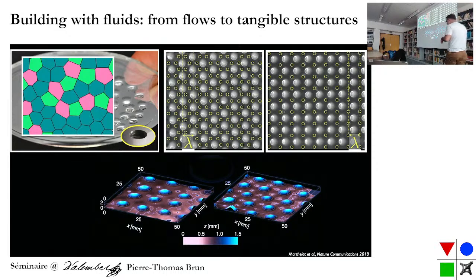Interestingly, you cannot push your luck too much, right? So if there is this mode, that's the expected mode. If you go too far, too small, or too big, then you're going to run into trouble. And this is about the same margin. So too small is about 40%, and too big is about 140%. Why we get this, for the 140%, it's more or less clear. You have a period doubling instability. For the 40%, it's not really clear what's going on.